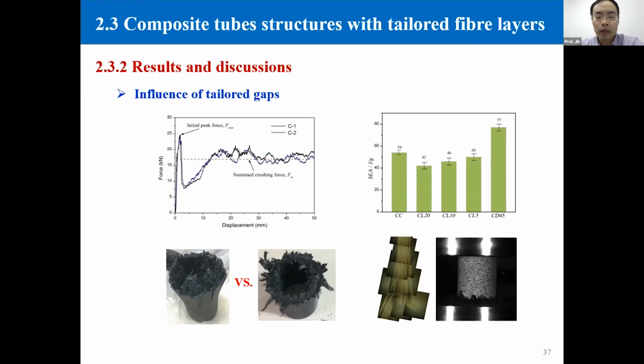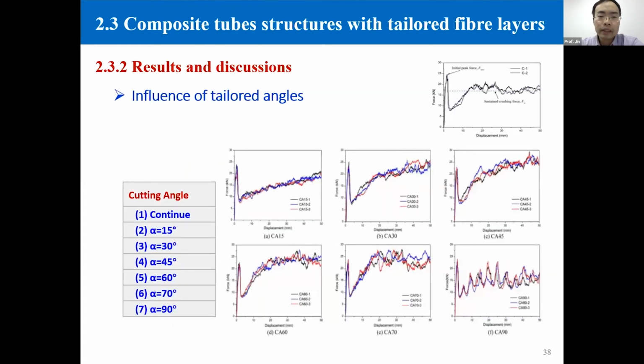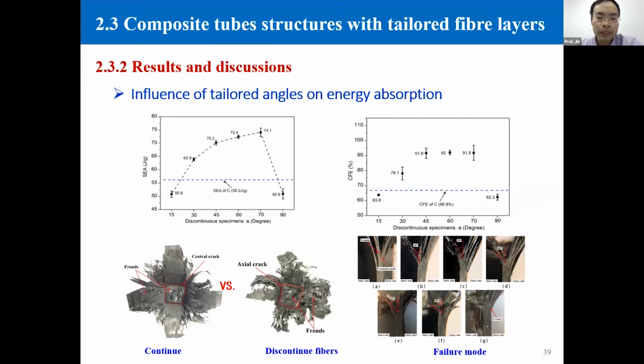We did a similar work. We did a compression test on those structures and compared the energy absorption of those structures, and we found when the cutting angle is up to 45 degrees we can get a better performance. And this is a sample with different cutting angles, from 15 degrees up to 90 degrees. We summarize the performance and found the energy absorption increases up to 75 degrees.